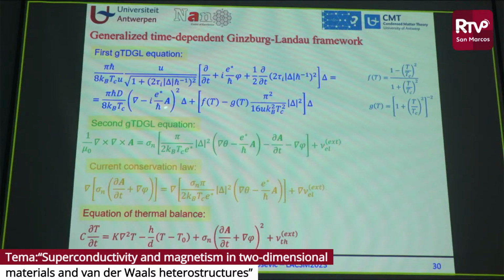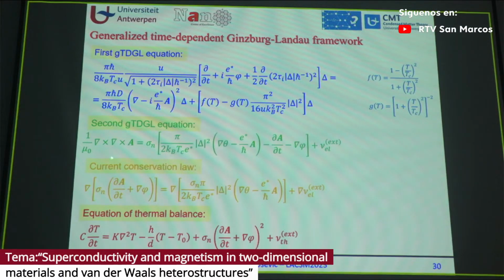Then we have the magnetic field that enters through this magnetic vector potential here. We have disorder that enters through inelastic scattering time here and here. Then the diffusion constant as well, which in the case of two-dimensional materials will be directly proportional to the Fermi velocity squared. So all of this can be parameterized from either first principles or from experiments that we talked about before. Then we have to solve the second Ginzburg-Landau equation, which describes the magnetic or diamagnetic properties of superconductors. And this is coupled, of course, because this A from here has to be fed back into this first equation. Then we have the current conservation law.